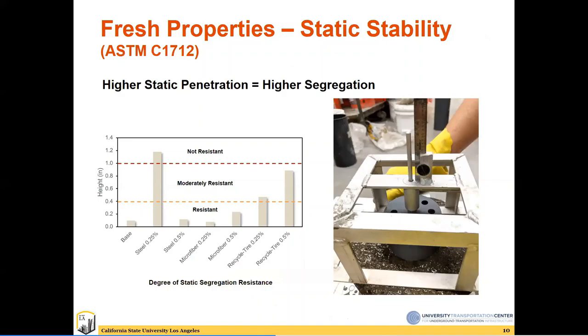Another test was to evaluate the static penetration and see if our mix is segregating. And you're basically dropping a needle on top of the slump cone as you have the SCC mix inside the slump cone and evaluate the height to see basically three levels of resistance to static segregation in terms of the mix that could be resistant, moderately resistant, or not resistant, which in this case, most of them are resistant or moderately resistant to static segregation.